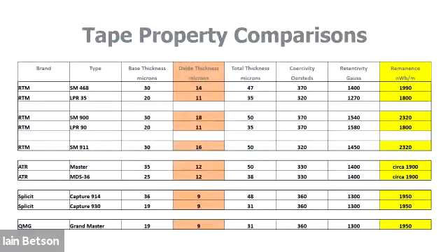Let's move on to the other bits and bobs I've mentioned. There are coercivity, retentivity, I should say, get that word out, and our remanence. Don't worry too much about the coercivity. It's measured in a thing called Oersteds, and it's just a figure here, 370 Oersteds, how much grunt we need to impart a magnetic signal into the tape, to realign all those little magnets into our nice thin tracks.